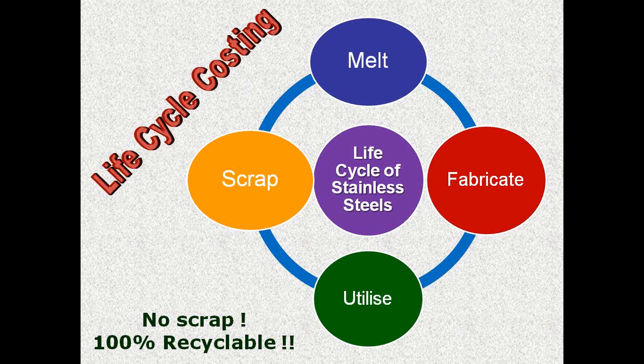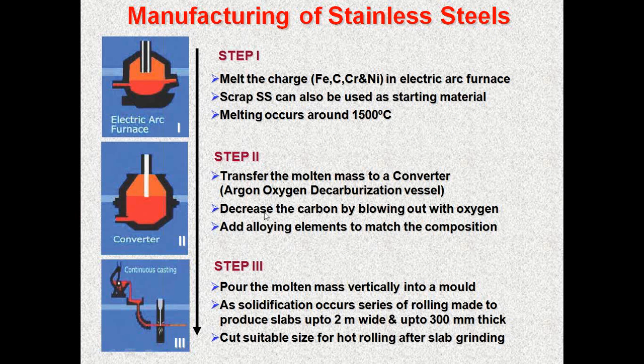How are they manufactured? The three simple steps I am putting here. The number one step is they are first melted in an electric arc furnace. After fixing the charge, the amount of chromium, nickel, carbon and iron, it is melted in an electric arc furnace. You can also use scrap SS directly as a starting material. The melting occurs around 1500 degrees, close to the melting point.